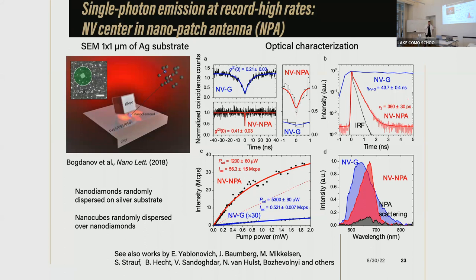which had such a size that at least some of them had only one single nitrogen vacancy, typically, let's say, 15 and 25 nanometers, 30 nanometers. And then we randomly also distributed these silver cubes on top. And just by chance, in some cases, a cube would end up sitting on the nanodiamond in between silver film and silver cube, so that this nanopatch antenna forms.